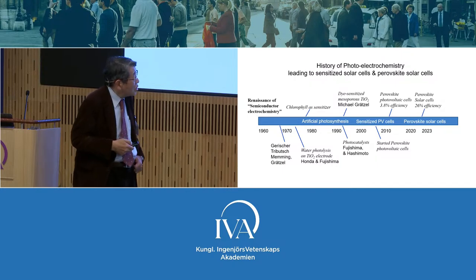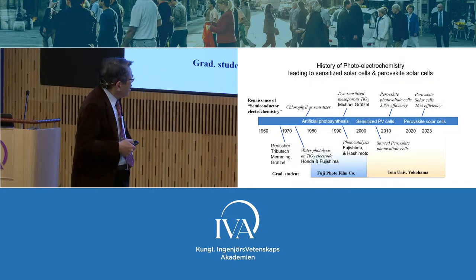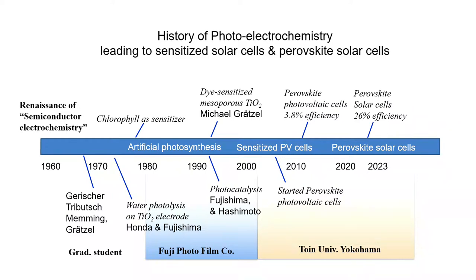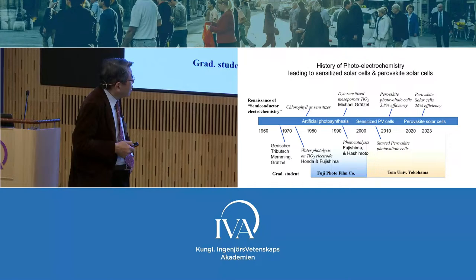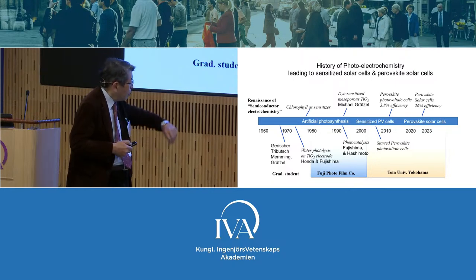So I had been working on dye-sensitized solar cell, and I spent 20 years in a company, Fuji Photofilm Company, and I switched to the university in 2001 and continued to work with a sensitized semiconductor. But we discovered, the happening is we found the perovskite crystal can sensitize this TiO2 electrode to produce the power. And we published the first paper in 2009 to show the efficiency, very low, 3.8%. But anyway, the perovskite solar cell has now achieved a very high efficiency, 26%.